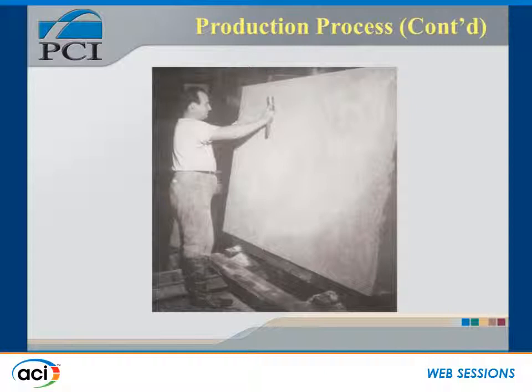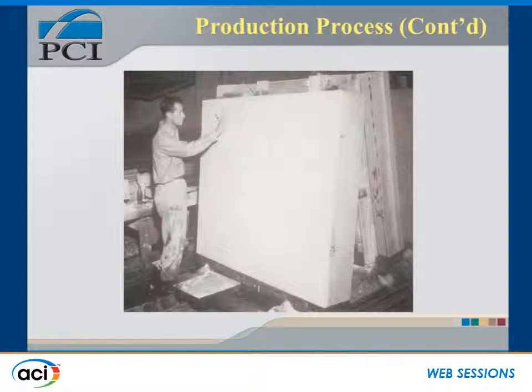The panels were initially cured for 3 days, being thoroughly sprayed with water at least twice a day. On the third day, a solution of 1 part of hydrochloric acid to 5 parts of water was applied and then brushed off using plenty of water. The proper degree of acid etching for uniform texture was then checked under a very strong light.